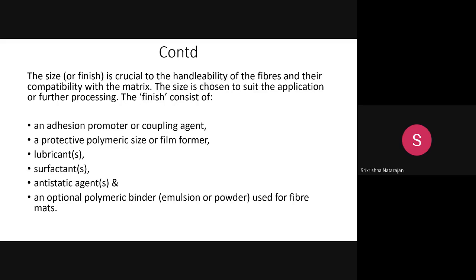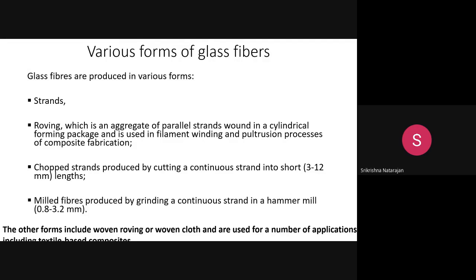In order to get a smooth feeling, when you touch glass you feel a smoothness. Okay, how do you get that smoothness? It is because of the sizing application. So for that you need to add this size or the finish. You add a number of finishing agents. Normally, a size will contain some 5-6 ingredients, like an adhesion promoter or a coupling agent, a protective polymer size or a film former, a lubricant like an oil, and a surfactant, an anti-static agent to prevent static charge accumulation, then an optional polymeric binder. So there are multiple ingredients in the size.